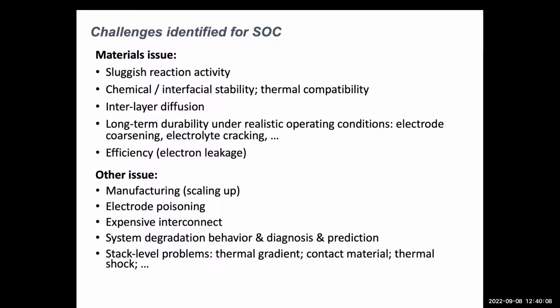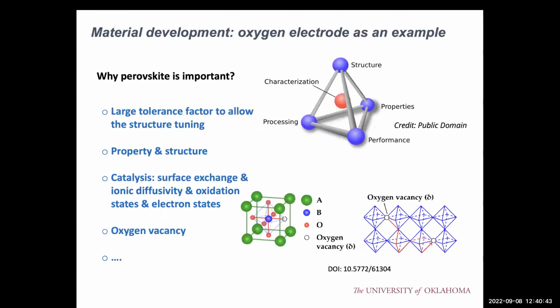the electrode, because the interconnect component contains some chromium. The chromium can evaporate and then form insulating materials at the interface, which can slow down the reaction. And some other things like expensive interconnect materials, how we are going to integrate, how we are going to predict the degradation behavior, and also the thermal mismatch or thermal gradient, which can also cause a failure of the SOC system.